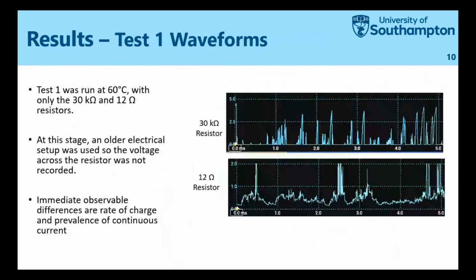So for the first test, I ran it at 60 degrees, and I only had the 30 kilo-ohm and 12 ohm resistors, so one very low current and one very high current scenario.